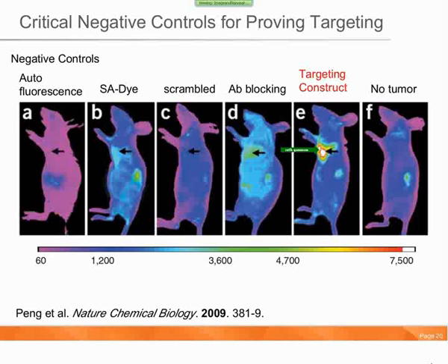Very recently published in PNAS by Young Chen and Steve Peralta is a strategy known as multi-stage tumor targeting. In this case, the nanoparticle is not directly conjugated to a reporter or a fluorophore. Instead, it has a linker group, in this case biotin, which can then be targeted by a second injection of fluorophore-loaded, in this case, streptavidin.